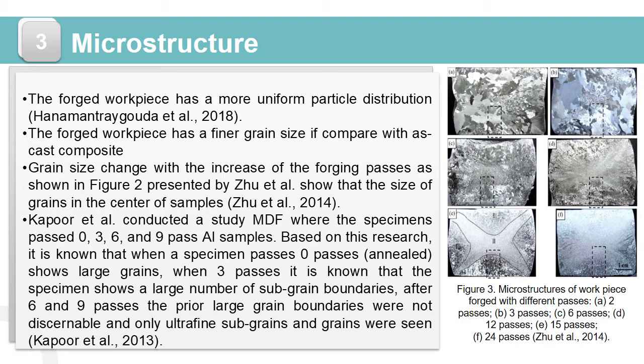It represents the recovery and recrystallization process. Then, the forged workpiece has a finer grain size compared with the as-cast composite. Grain size changes with the increase of the forging pass, as shown in figure 3, presented by Zhu et al. In line with Yu, Kapoor et al. conducted a study on multidirectional forging where the specimen passed 0, 3, 6, and 9 passes.